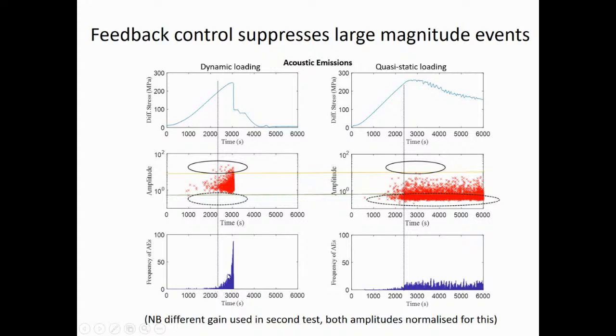And then you get, I've already shown this, the inverse power law acceleration and the fact that we deliberately slowed it down to a constant strain rate here. So what this means is that maybe if you want to suppress big events, the way to do it is maybe not to record the big events on their own, like you would have to do for, say, a traffic light system. Maybe the best thing to do is actually to feedback on the event rate. And that's something for discussion, in terms of how one might manage the risk of an induced seismicity setting.